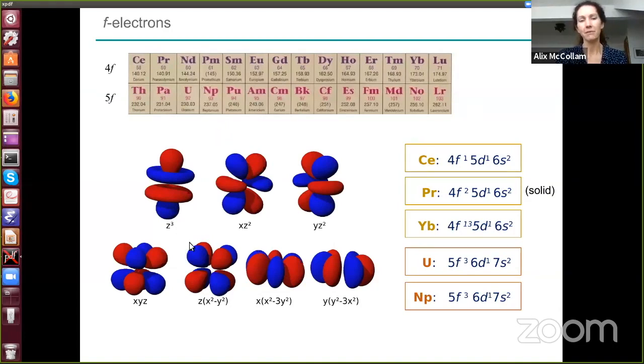So this is a reminder of the f orbitals. And the thing about the f electrons is that they're spatially rather close to the core, the nuclear core. So the f electrons tend to be localized near the nucleus or near the atomic core, but energetically they're almost degenerate with the s and the d electrons. So spatially localized, but energetically quite comparable to the conduction electrons, which allows for these interactions between the f electrons and the conduction electrons that make the behavior of these materials special.